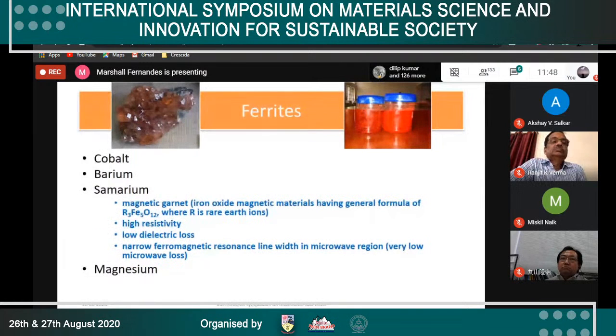I'm talking about samarium ferrite. It has high resistivity, low dielectric loss, and a narrow ferromagnetic resonance line width in the microwave region, so it has very low microwave loss. Then magnesium ferrite.